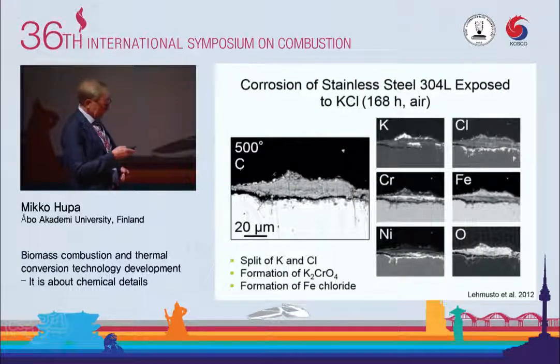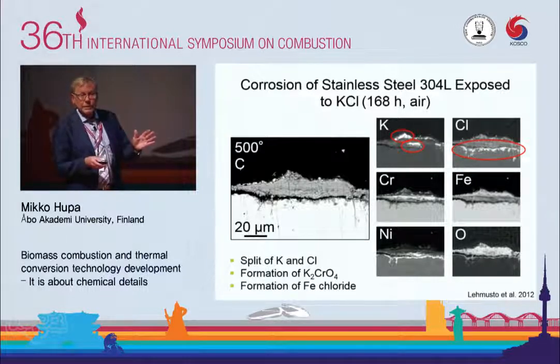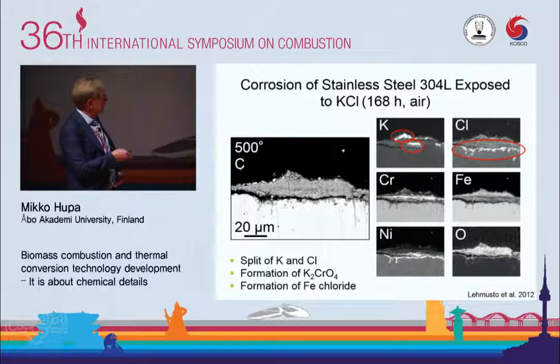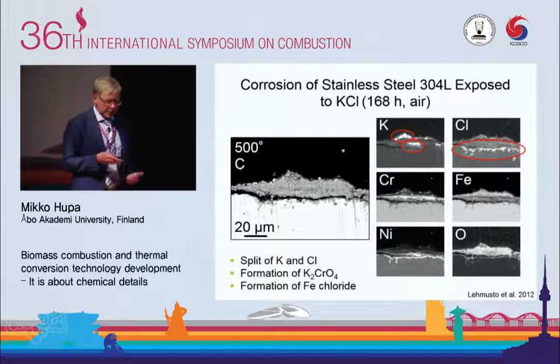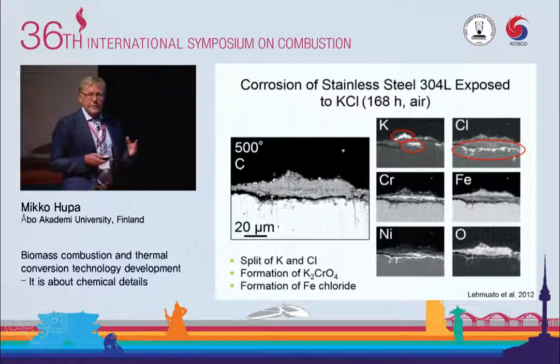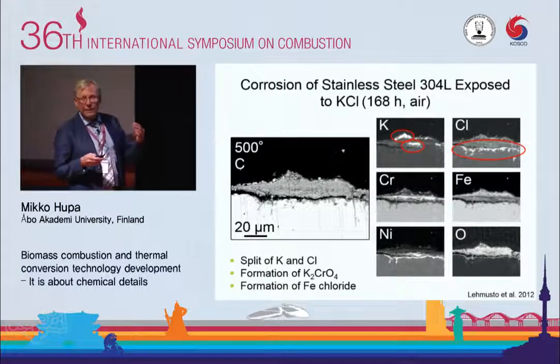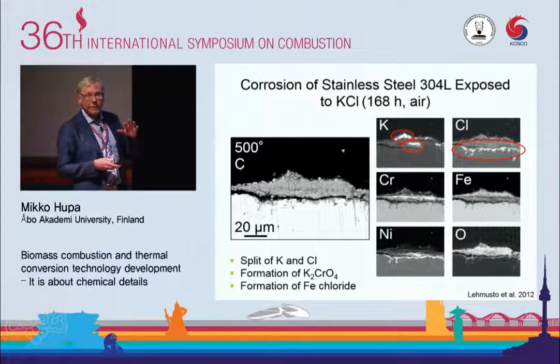I don't go deeper into this, but the key is that when we do this kind of microscopy, we can see that after a week exposure, the potassium is still on the surface, but it is no longer together with chlorine. So there is a split of potassium chloride, but this is not because of the sulfur dioxide. It's just straight on the surface. And we know from many tests it's an interesting formation of potassium chromate, the chromium layer on the surface. And that chromate formation has not really been so well reported before. Now it is a great, interesting thing. And in which conditions does the chromate form? It doesn't form for a long while. It's just an intermediate which breaks the surface.